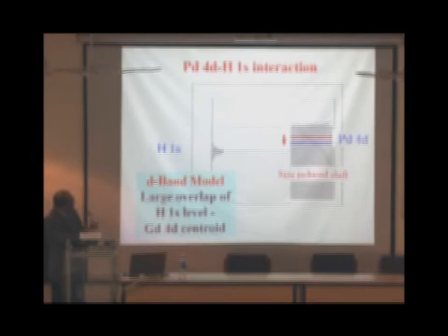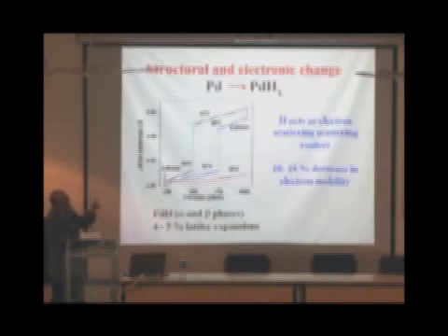This is called the d-band model, and what we observed is when we change the size of the palladium from 30 nanometers to around 5 nanometers, there is a shift of the palladium 4d centroid away from the Fermi energy, which is responsible for increased interaction of palladium with hydrogen. And this is one of the reasons. Presence of voids, increased interaction of palladium with hydrogen, and there are two other things which take place when hydrogen is going into palladium. One of them is that hydrogen acts like scattering centers for electrons. So when hydrogen goes into palladium, it will increase the electrical resistivity of palladium because mobility will be affected because of the scattering process.